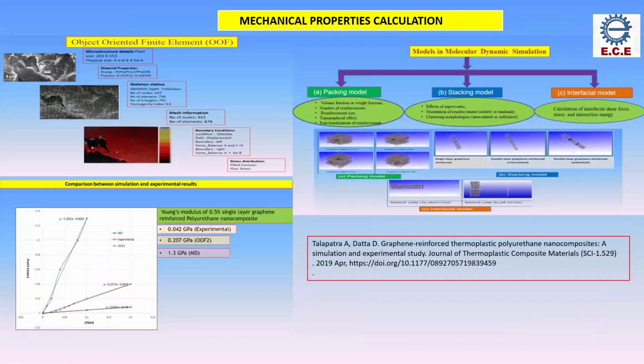And one of the works was done using object-oriented finite element and molecular dynamics simulations. We developed the graphene-based nanocomposite or thermoplastic composite and basically developed the microstructure. With the help of the microstructure, we used the object-oriented finite element as well as the molecular simulations. You can see that in the experimental procedure,